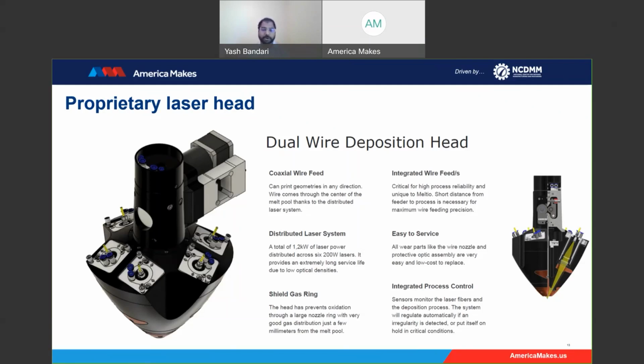You can have one spot at a higher wattage compared to the trailing spot, thereby giving some kind of preheat, and then you're also manipulating the solidification because you've got different laser power. All of these things make this deposition head very unique. And you can feed not only one wire, but more than one material, though only one material into the melt pool at a time. So there might be some situations where you want to print the lower section of a component with material A, and the upper section with material B. That is possible, and it is done entirely in an automated fashion.